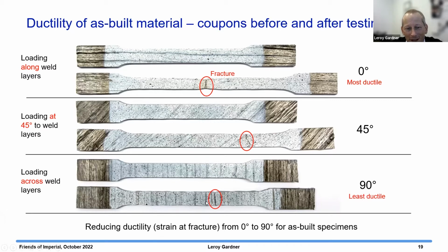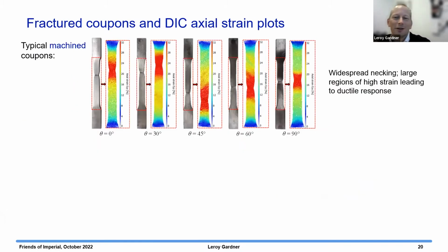And the reason for that is in the 90 degree direction, you've got your cross-sectional area kind of going up and down, and all of the deformation tends to run into the minimum cross-section. And so the strains become very much more localized, and therefore you get less ductility over the full length of the coupon. So that's logical. And you can actually see it on these strain plots.